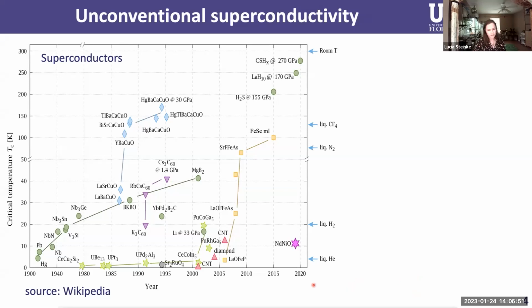So here's a list of some superconductors that are known by now, listed by their critical temperature and the year in which they were discovered. And for the first 75 years of scientists studying superconductors, actually most of the, or all of the known superconductors were non-magnetic metals. It was found that if you put even the tiniest amount of magnetic impurities into a superconductor, that would destroy the superconductivity. So it was believed that magnetism and superconductivity were mutually exclusive.